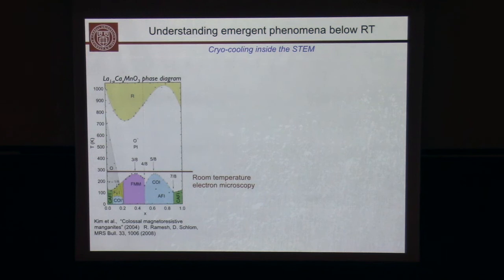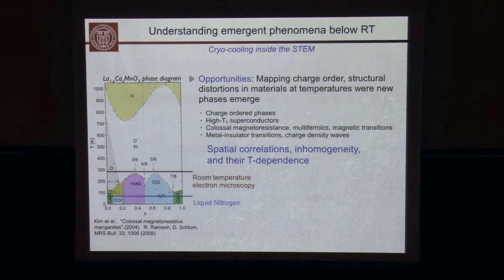So what I have set out to do with my group in the last few years is actually pushing this. Well, I had bigger hopes of being able to go continuously from room temperature to liquid nitrogen. I think that will take me another 5 years, but right now I'm at liquid nitrogen temperature, where we can measure with ultra-high precision, so 2 picometers or so, the position of atoms, and we have made progress in spectroscopy as well. So if we can actually do this, what are the opportunities?